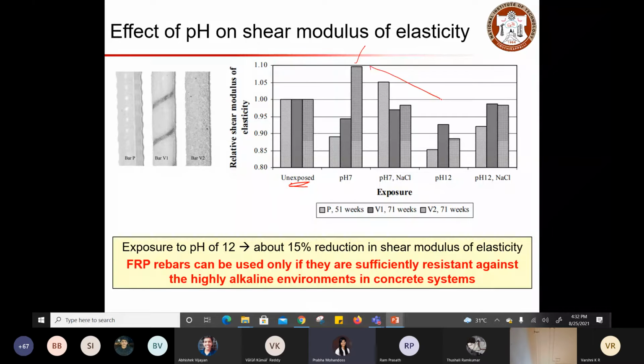So you see the drastic reduction in the shear modulus of elasticity when you increase the exposure, as well as when you increase the pH value. So this basically indicates you have to choose an FRP rebar which can sustain the highly alkaline environment. If it is not able to sustain the high alkaline environment, then the shear modulus of elasticity would be drastically reduced. And if that got reduced, your structure becomes less stiff. So to have better stiffness, you need to select fibers that are stable in a highly alkaline environment. So that's a point here to understand.